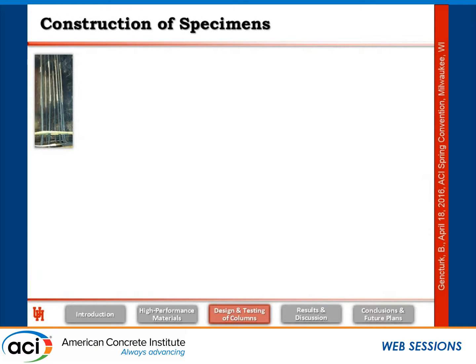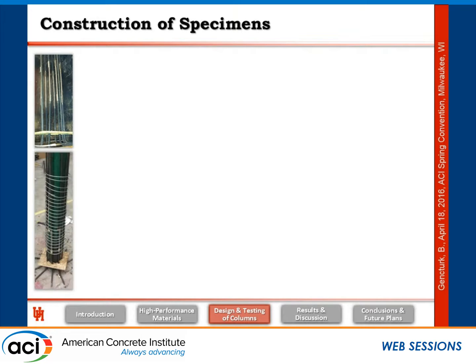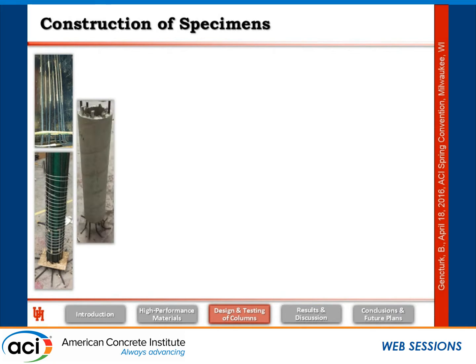So this is how we constructed these specimens. These are kind of small, so it was a little bit tedious to construct these. So you see on the upper left here is the SMA bars with the couplers connected to the steel. Here we put a tube inside this cage, so that it serves as the inside formwork, and we put the spiral reinforcement around it, and then we had an exterior formwork. We poured the ECC in between the two.